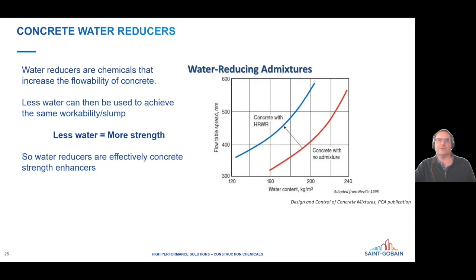So these chemicals do something very simple. They just increase the workability or the flowability of the concrete. And so what that means is that if you're aiming for a certain workability, you can use less water when you add the additive, and that's why they're called water reducers. And this is very important because less water means more strength. So in a way, a water reducer really is a very effective concrete strength enhancer when you use it that way.